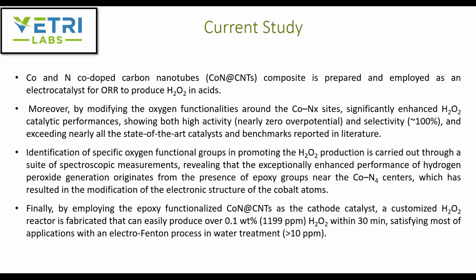They did a series of spectroscopic measurements to identify the specific functional groups promoting this peroxide production, and revealed that the exceptionally enhanced performance originates from the presence of epoxy groups near the CoN4 centers, which resulted in the modification of the electronic structure of these cobalt atoms. Finally, by employing this epoxy functionalized cobalt nitrogen doped carbon nanotube as the cathode catalyst, a customized peroxide reactor was fabricated that could easily produce about 1200 ppm within 30 minutes, which could satisfy most applications such as in water treatment.